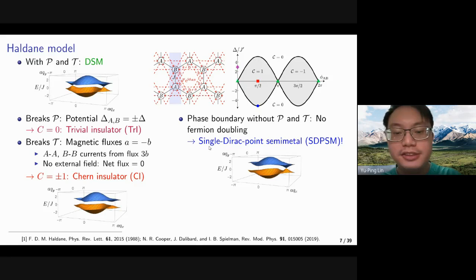So it turns out that if we look at the phase boundary, it should be gapless. So we should at least have one gapless point. And without inversion and time reversal symmetry, we are not required to have a pair of gapless points. We can have just one. And if we look at the band structure, there is indeed only one gapless point. So it is a single-Dirac-point semimetal.